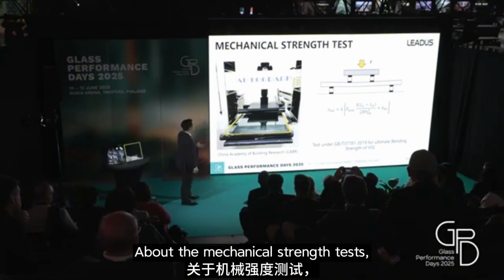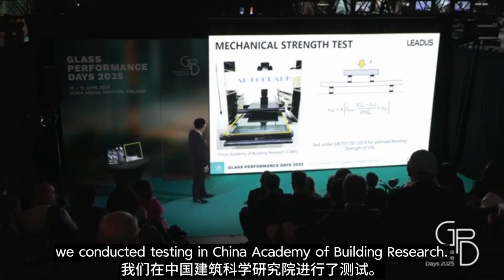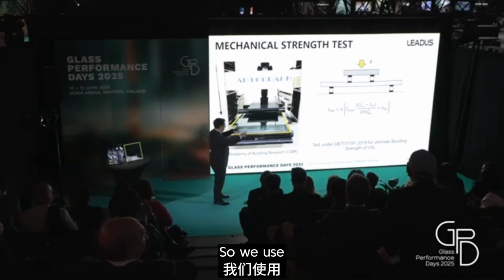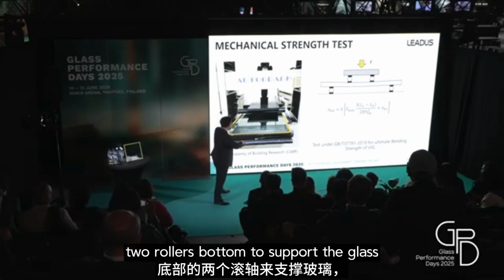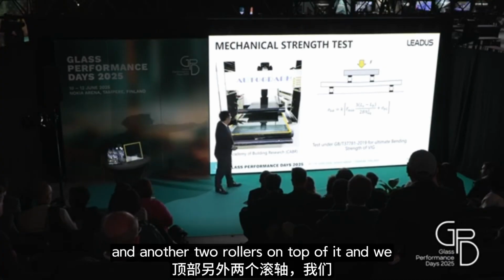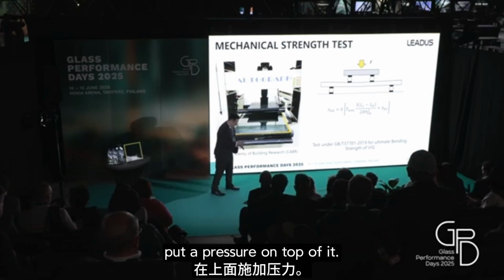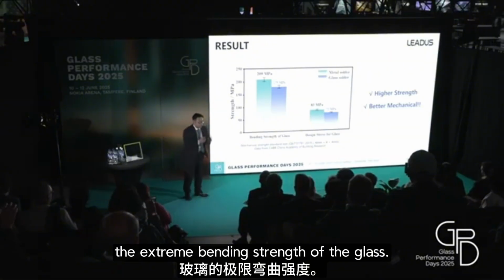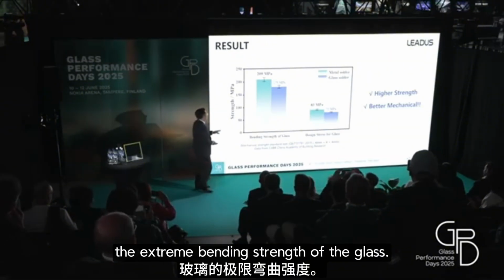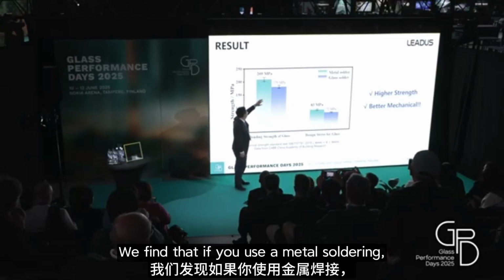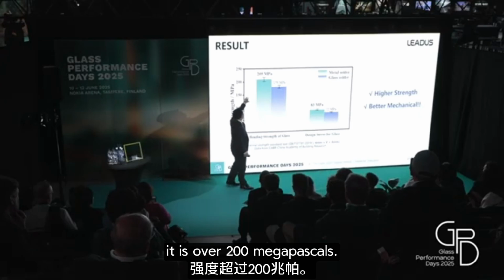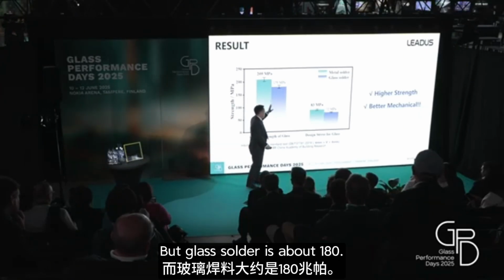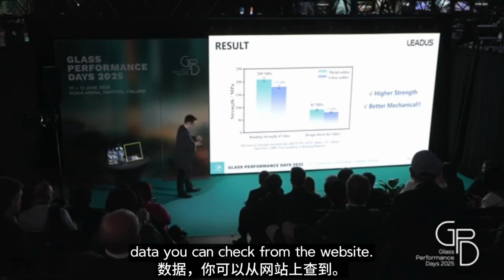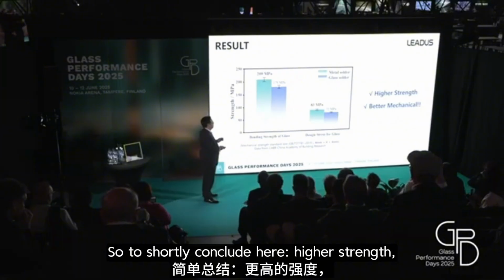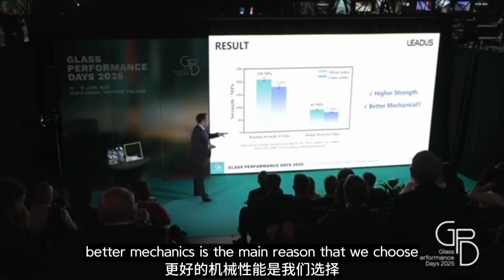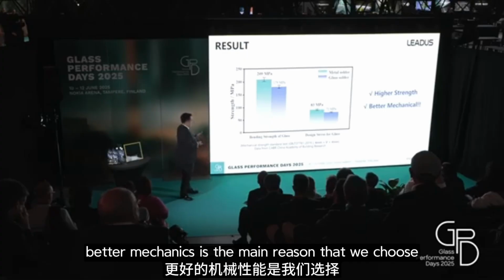About the mechanical strength tests, we conducted testing at the China Academy of Building Research. We use two rollers on the bottom to support the glass, and another two rollers on top of it, and we put pressure on top. And what did we find? The ultimate bending strength of the glass with metal sealing is over 200 megapascal, but glass solder is about 180. That is public data you can check on the website. To conclude briefly, higher strength and better mechanical performance is the main reason we choose metal as our sealing material.